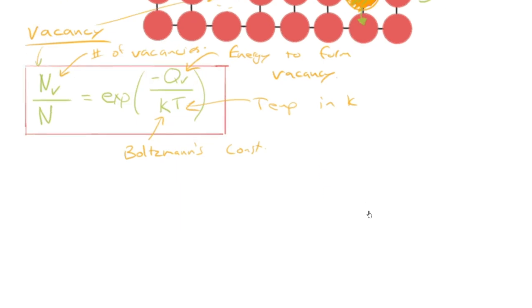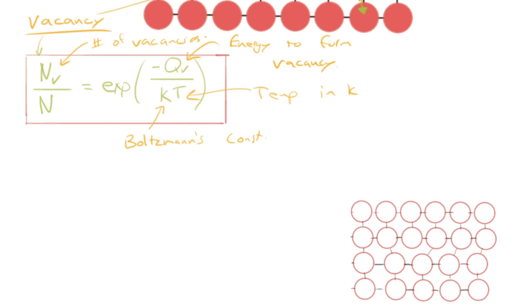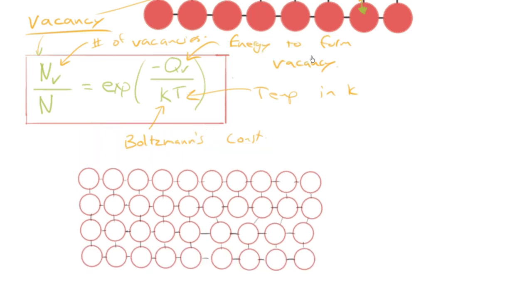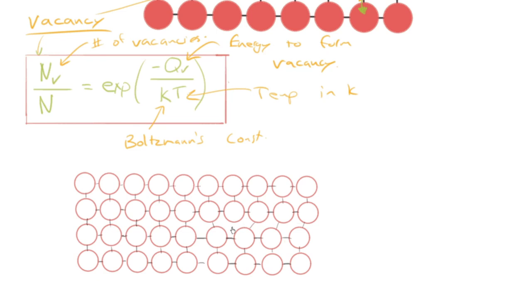So the other thing I wanted to do, I promised you, is I would look at how these atoms interact with dislocations. Now, it is a way of explaining mechanical behavior. So I'm just giving myself a bit of space there. And so what I've drawn here now is a little dislocation that you're familiar with from the previous video. And what I'm going to do is say, you know, what if we introduce now an interstitial atom, like we discussed just above? Well, you know that's going to push these atoms apart like this, create some lattice strain, it occupies a bit of space in the lattice. And there's also though, associated with this dislocation, there's also some strain energy. So this extra half plane of atoms, these two atoms here, have sort of occupied some space in the lattice. And so they're compressing the lattice here above the dislocation, and below the lattice is in tension. So there's all this residual stress.